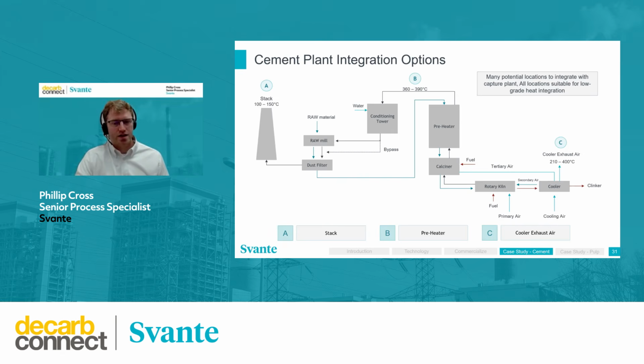So the key drivers affecting integration: first, tie-in location. The flue gas CO2 composition can be higher than 25% on a dry basis when taken after the preheater due to no air dilution. So higher partial pressures of CO2 often drive it into the beds, making the system more efficient. Also, raw material characteristics of the mills. So these mills have to dry their material.